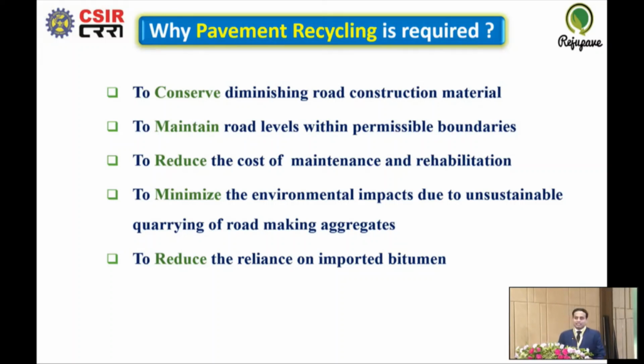In this direction, the CSIR Central Road Research Institute worked with Verma Industries, and under a sponsored research project, we have developed India's first bituminous rejuvenator called Reju-Pave, which facilitates 60 to 70% reclaimed asphalt pavement material utilization in bituminous mixes. Presently, as per the current practices prevalent under IRC and MORTH specification, we can hardly reutilize 20 to 25% RAP in the recycled bituminous mixes. But with the help of this Reju-Pave technology, we can reuse 60 to 70% RAP in the bituminous mix.